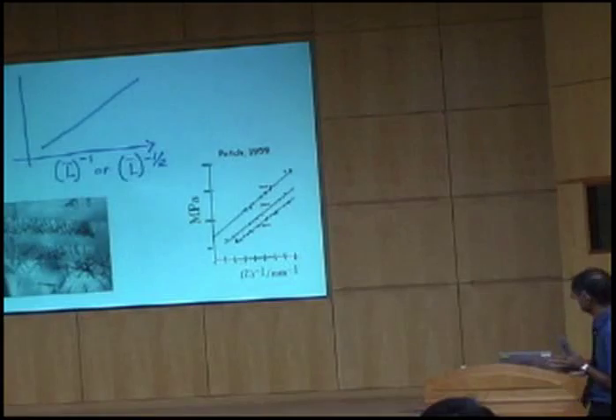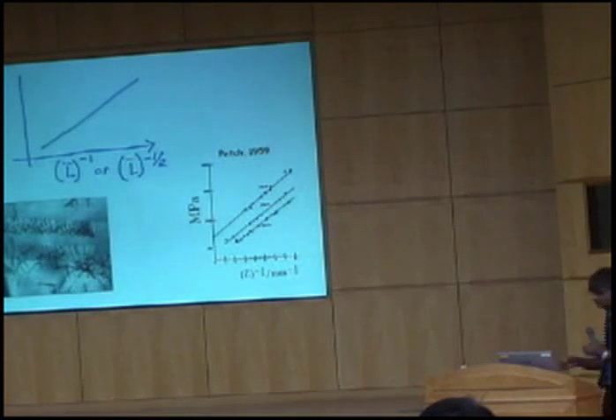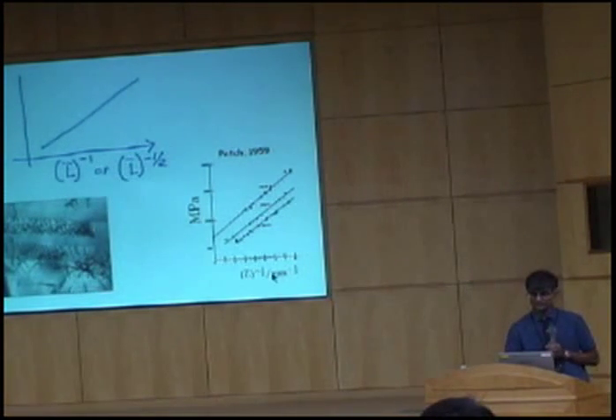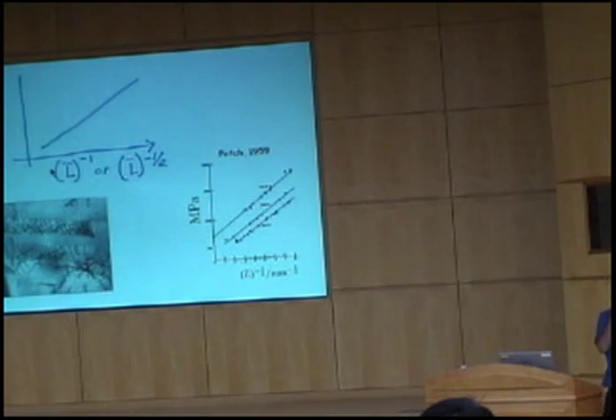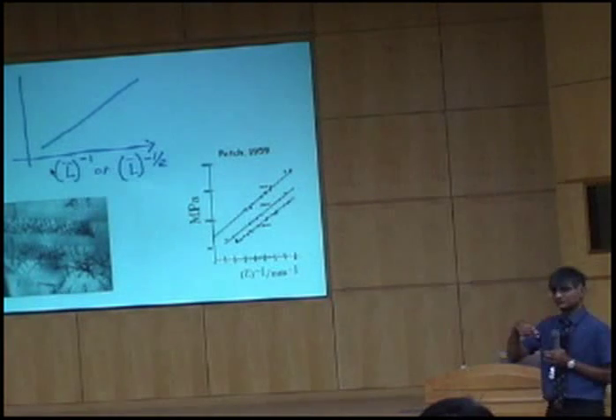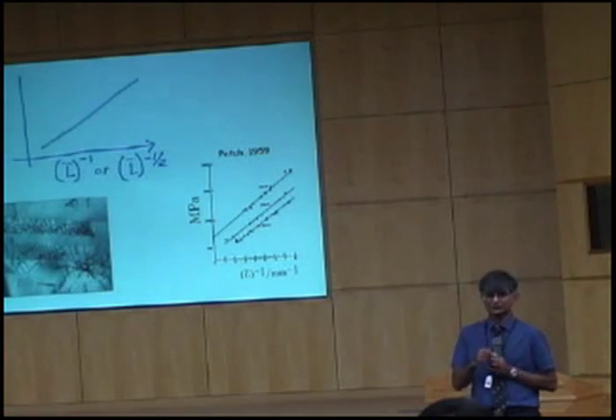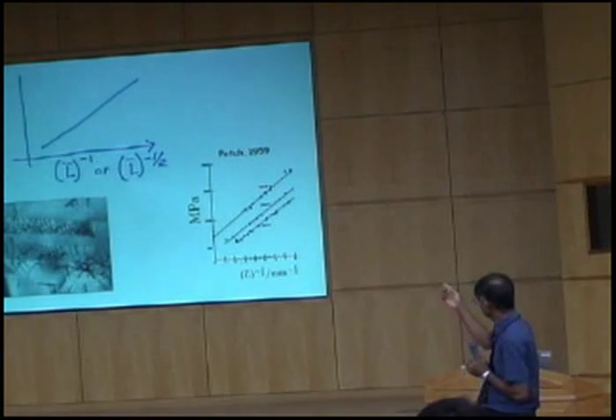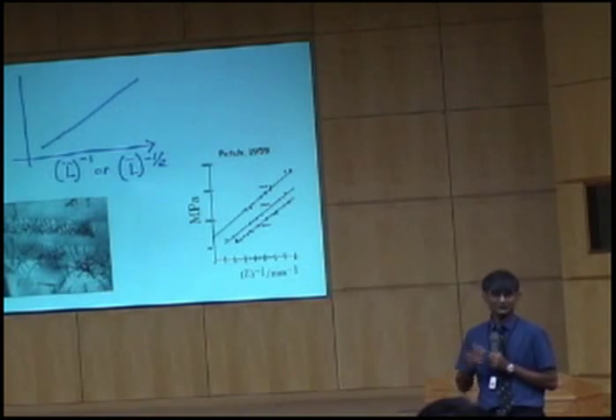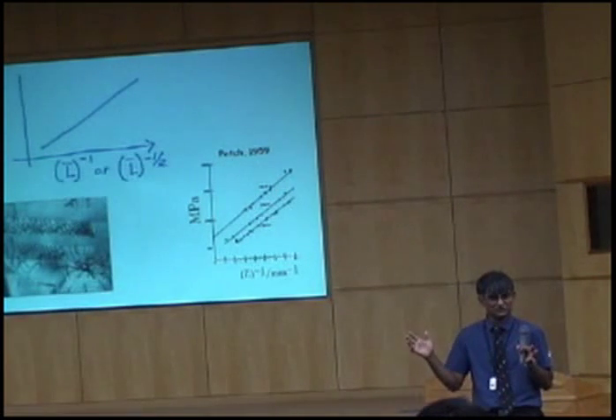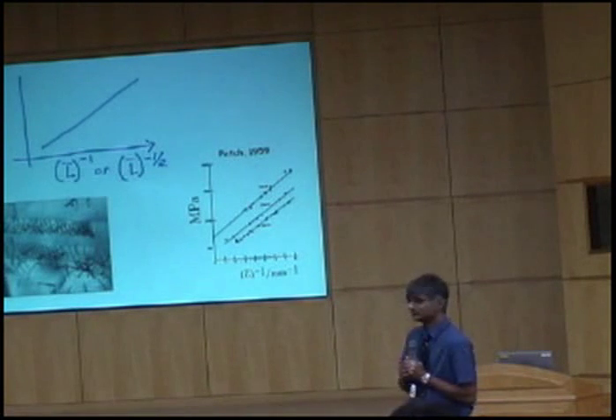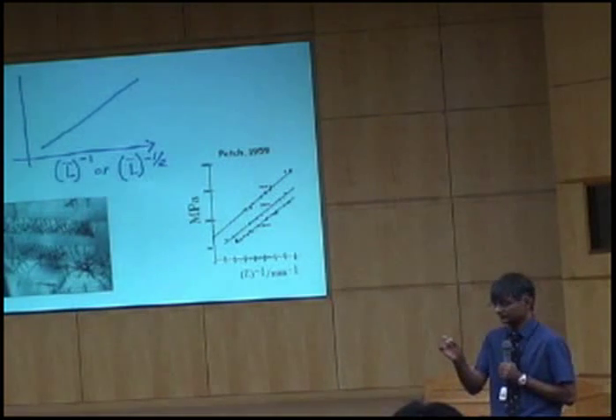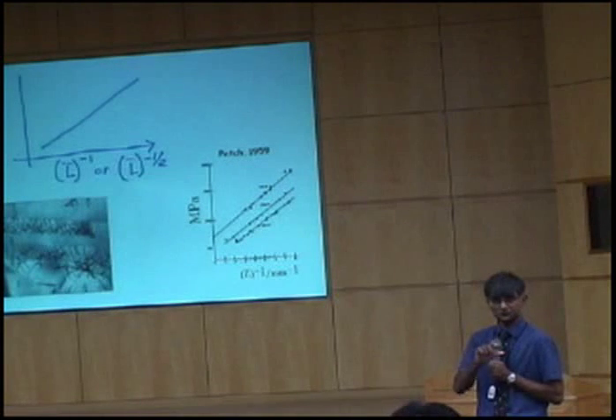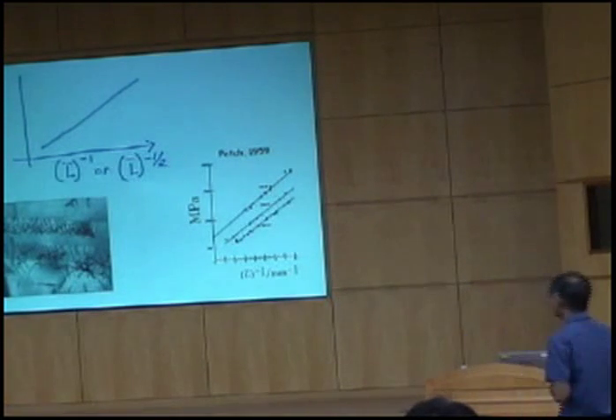Okay? And for that, the relationship is not 1 upon the square root of the grain size, but rather 1 upon the grain size. Okay? Unfortunately, if you do experimental measurements and you plot the strength either as a function of the grain size to the minus 1 or minus a half, you still get a straight line because those experiments don't cover a wide enough range. But theoretically, it should be 1 upon the grain size. So if we reduce the thickness by a factor of 2, we should double the strength. Okay.